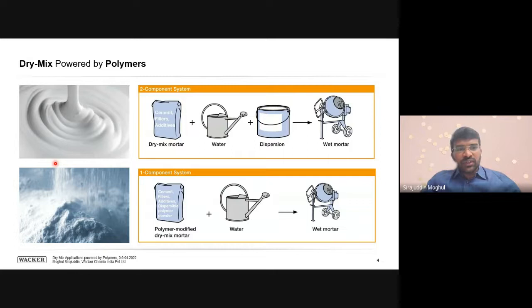Coming to why we actually wanted to have dispersible polymer powder: in the beginning, before the 1950s, all the systems used to be two component systems. We needed cement mix mortar, which would be packed in a bag, and you add water at site. In addition to water, we used to add dispersion at site. So one component is the dry mix mortar, and the other component is dispersion. These are the two components, and then we mix them and make the wet mortar.